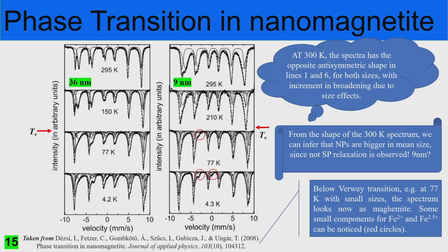And from the shape of the 300 Kelvin spectrum, we can infer, as a first approximation, that the nanoparticles are bigger in mean size, because we don't have a collapsed spectrum here. If we had a superparamagnetic spectrum, we would hope that these 9 nanometers would be collapsed, or at least have intermediate relaxation components. And this is not, this is a blocked magnetic state. So it's really 9 nanometers. We have to see about this.